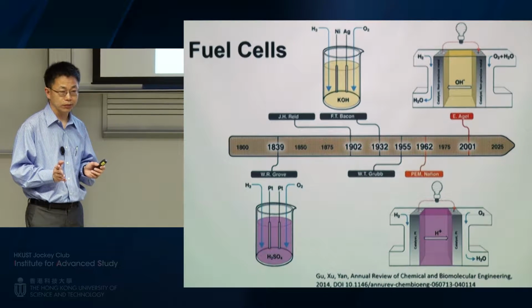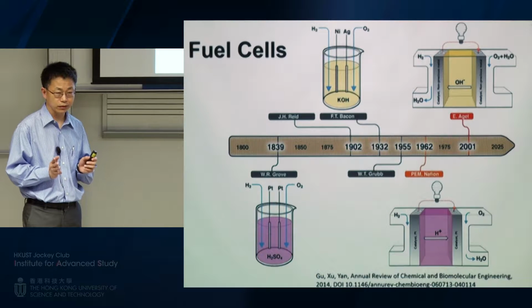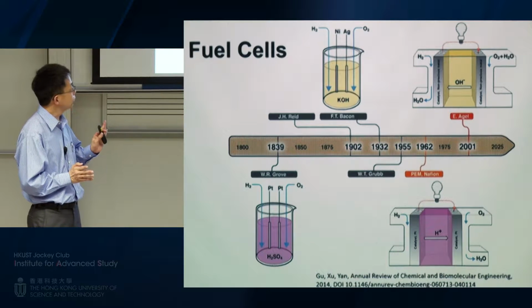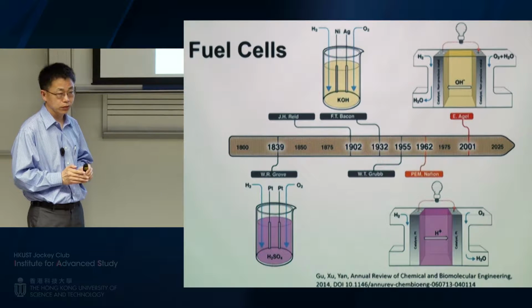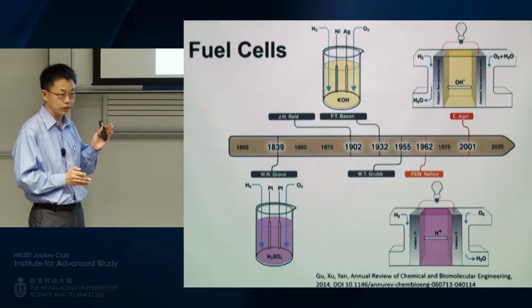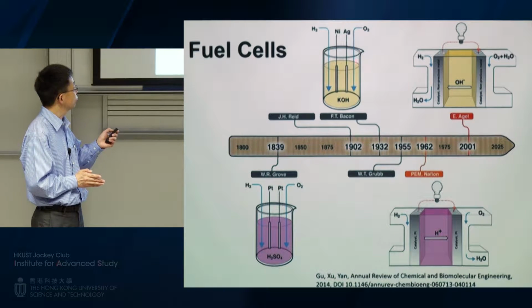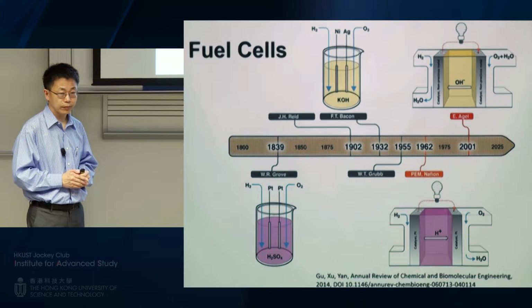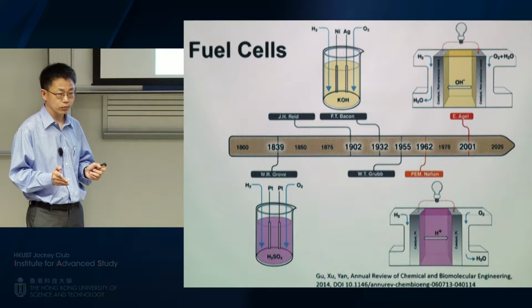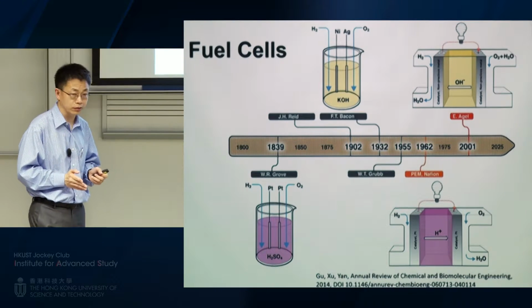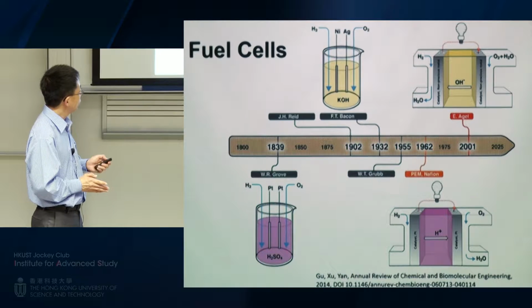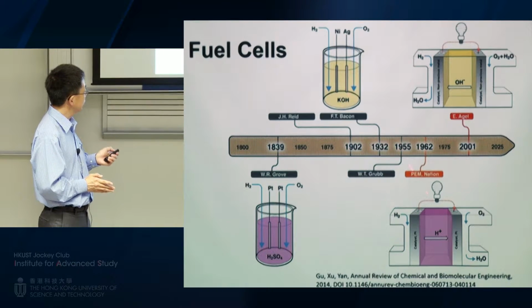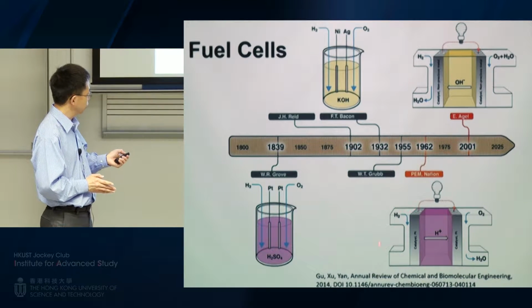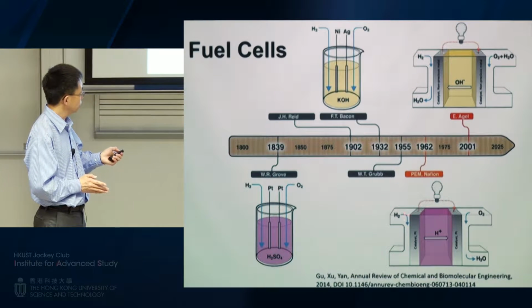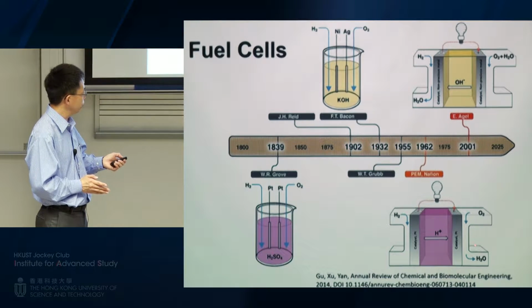And then about 100 years later, it was realized we don't have to use sulfuric acid. We can use potassium hydroxide. And once you make this very simple switch, you can use non-precious metals instead of platinum. You can use nickel for hydrogen oxidation, and you can use silver for oxygen reduction. So the question is, why didn't we spend the past 20 or 30 years to work on this kind of technology? Instead, we really spent most of our investment on this proton exchange membrane fuel cell.